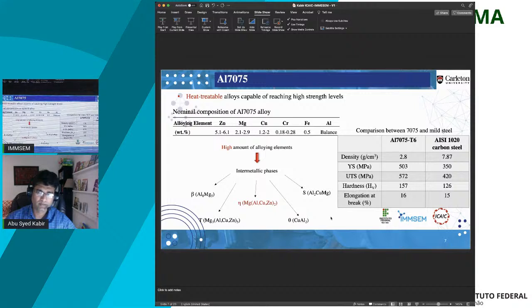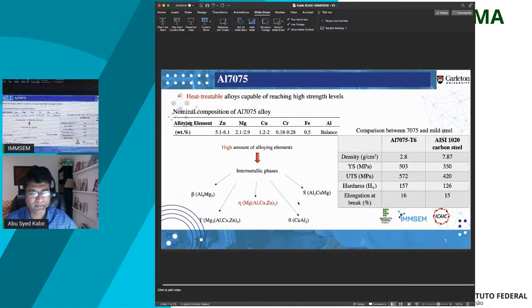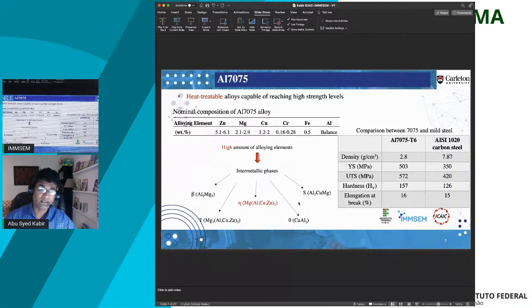As we have a very high amount of alloying elements in the 7075, depending on the heating and cooling cycle, we get different kinds of intermetallic phases. So we can see there could be beta phase, the T phase, the eta phase, the theta phase, and the S phase. All can form simultaneously, or some specifics can form at the same time, depending on the heating and cooling cycle.